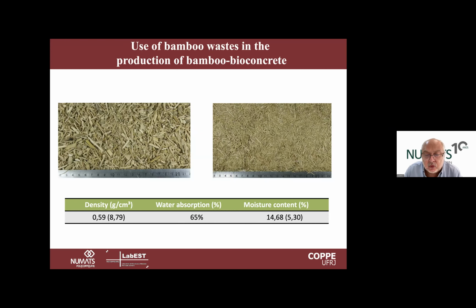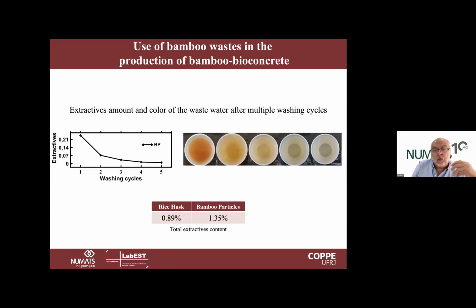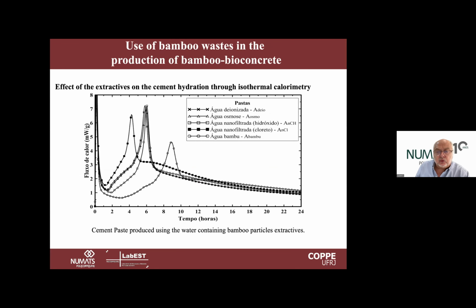We also determine the water absorption because in the mix design we need to compensate for this water. The extractives that come with bamboo can affect the hydration of the cementitious matrix, giving a certain delaying effect in the hydration. So we studied washing this material or doing some filtration using nanofilters, and we also used some chlorides to recover the velocity of the hydration reaction. But bamboo is not a big problem, though it has some delay.